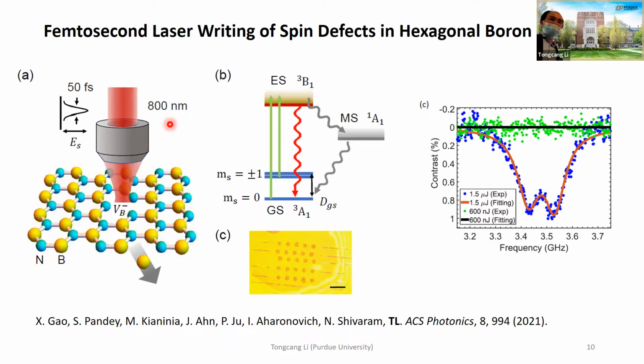One possibility is, for example, if the energy is too high, it may create not just single vacancies but clusters of these defects, and then they are not good for this ODMR measurement. So using the femtosecond laser, this one, not really. So that's why we want to move forward.